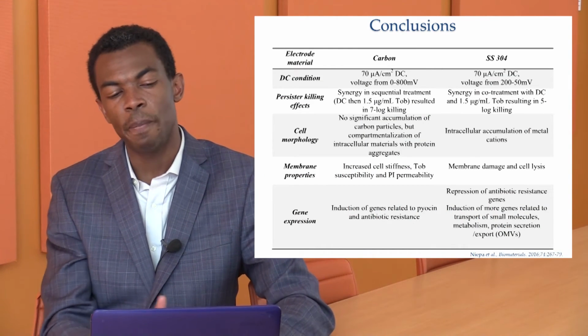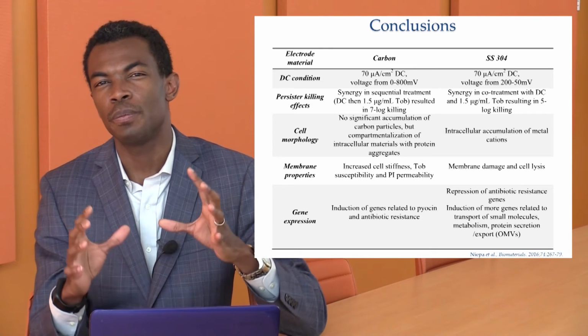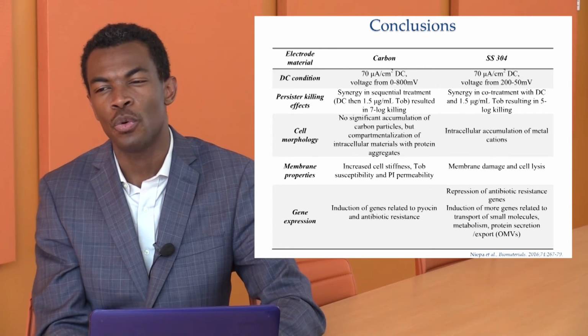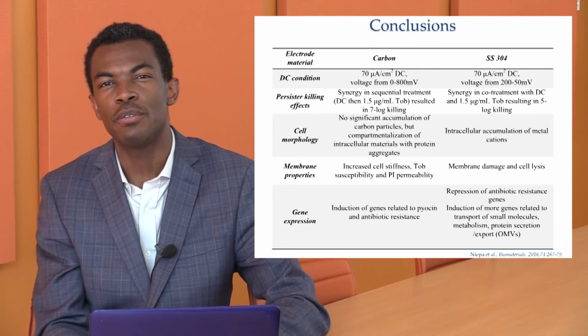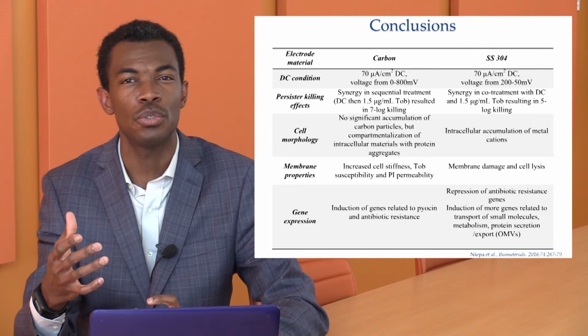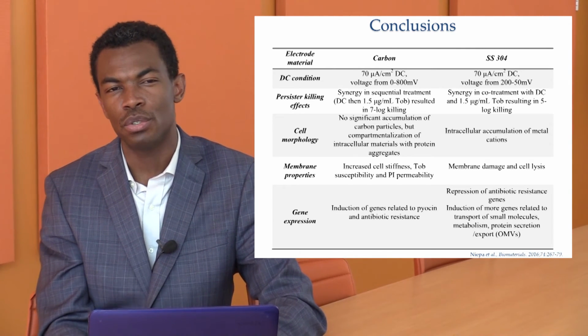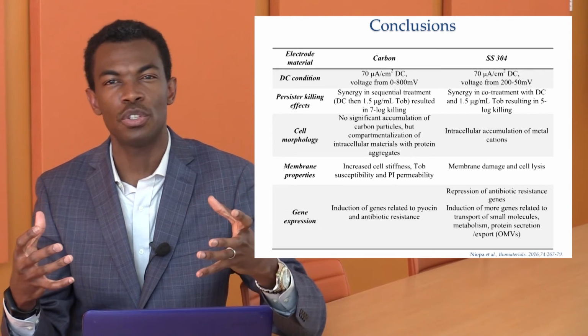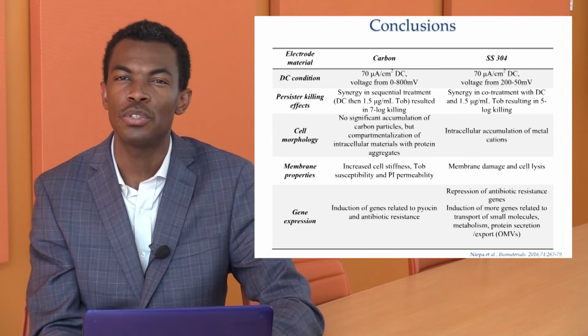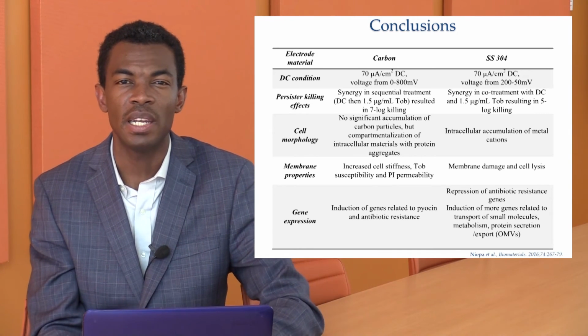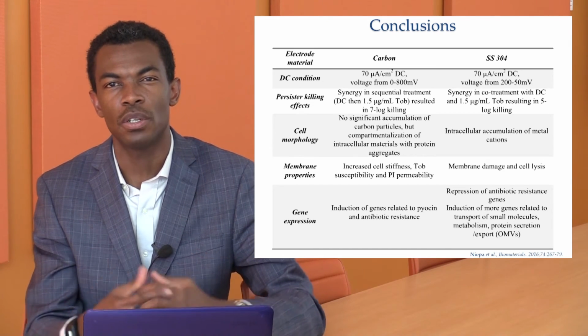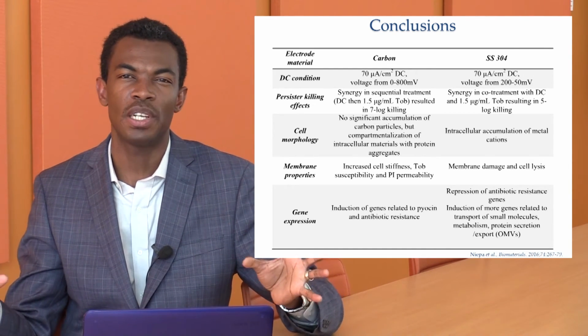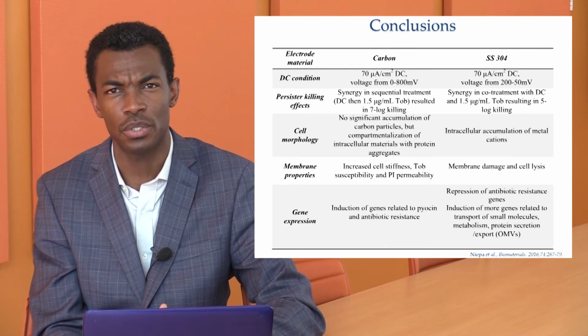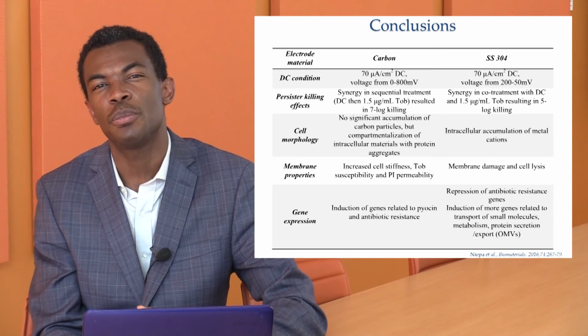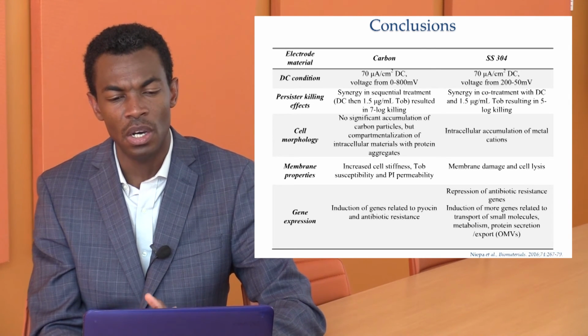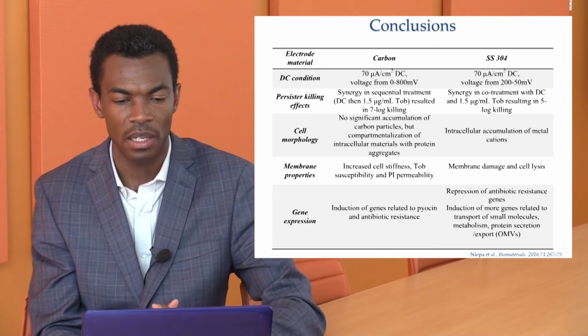So, to conclude, I would say that we did show in a very clear manner that we can perform some treatment if we have to innovate on designing some technology in order to cure infection. This will lead us to understand the makeup of the electrode material and how we can deliver some electrochemical current to cells embedded in biofilm, and then understand what would be the effect of such treatment on the cells. But focusing on two electrode materials, carbon electrode versus stainless steel electrode, we get different responses. Performing the treatment with 70 microampere per centimeter square of DC affects the cells greatly.